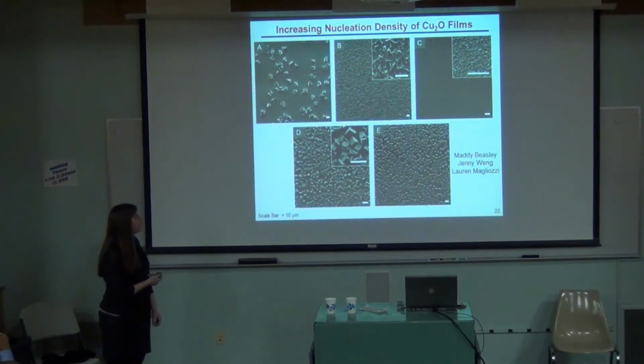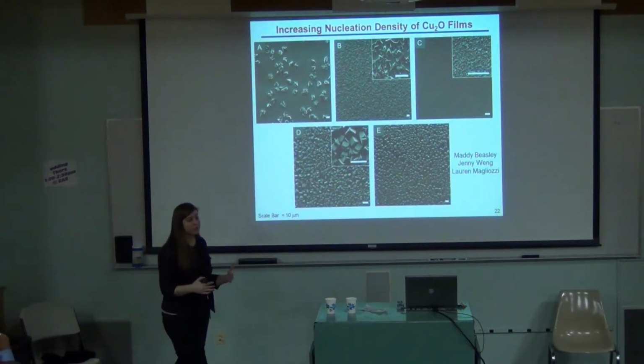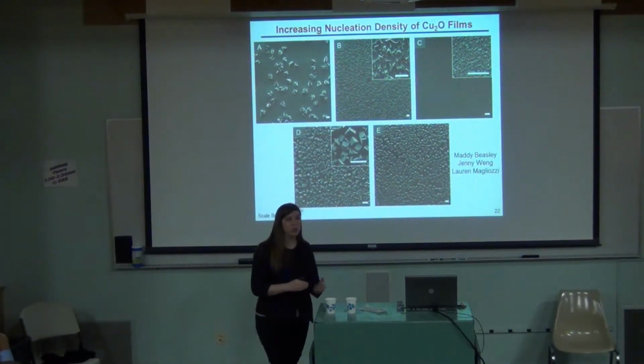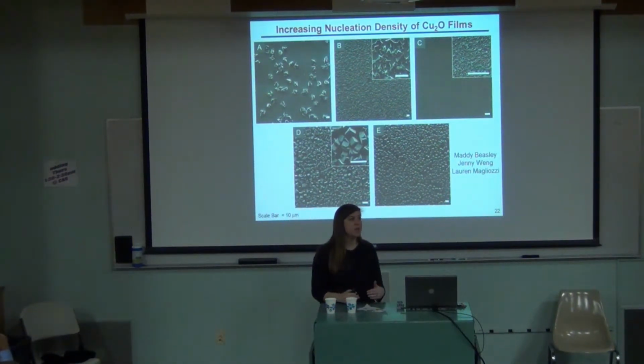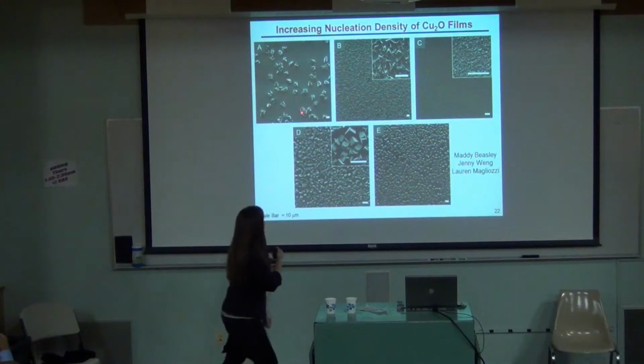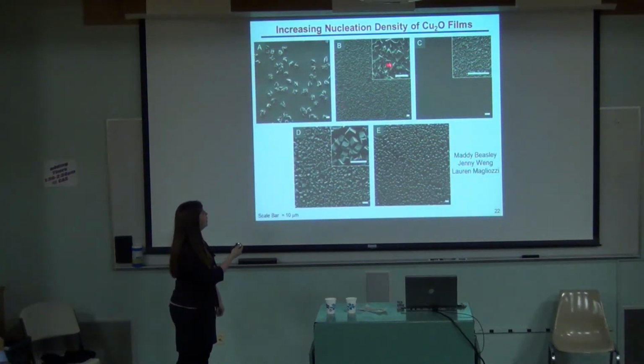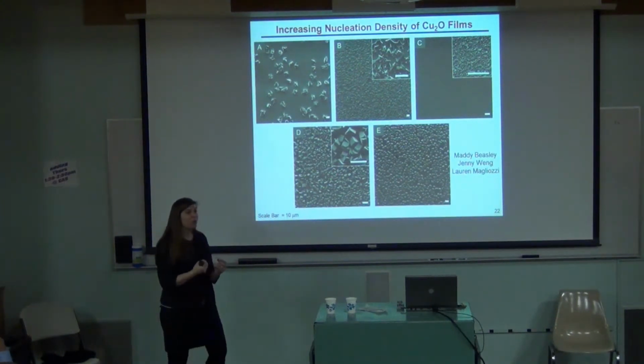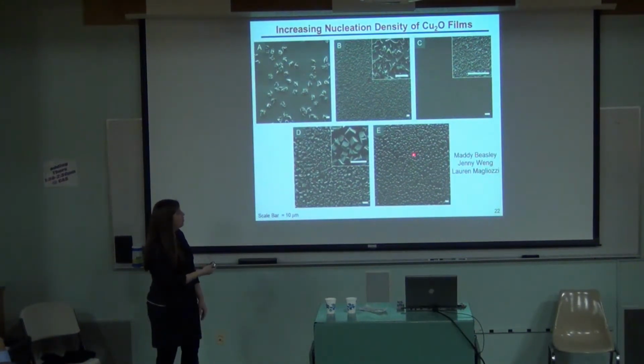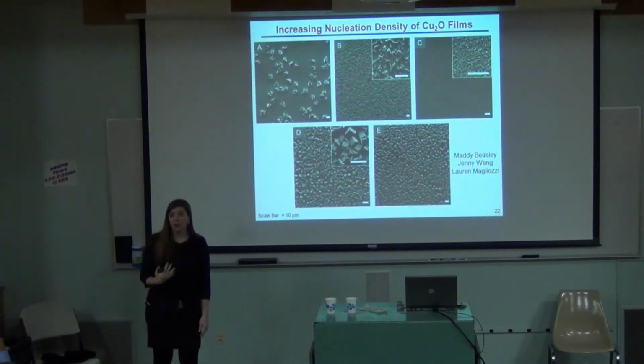This slide only shows three different students' work, but we need to take the film and make them a very densely packed film. The reason for this is when we're studying different properties, we want to make sure we're actually studying the properties of the crystals themselves and not just of the background or of something that is on the conducting slide that we put them on. So an electrode, we deposit on these conductive electrodes, and if we don't cover the whole film, so this one doesn't cover the whole film, and you can see ITO in the background. This one also doesn't cover the whole film. This one does, and they're really tiny. The smaller the crystal, the better the photocurrent. And so that is what we did with octahedral. We got pretty far with cubic, and we didn't get that far at all with truncated.